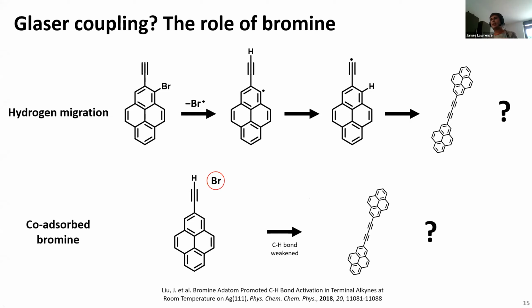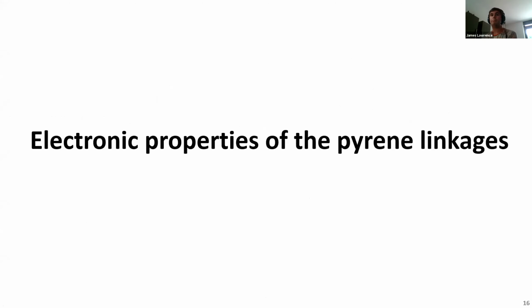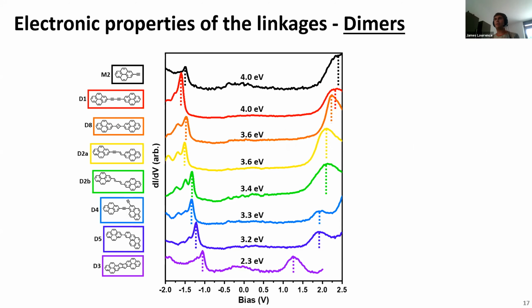come back from this aside and now turn to the electronic properties of the different links between the pyrene moieties. Obviously we've got so many different products on the surface that we can study loads of different types of linkages. So on the next slide, I'm just going to show you a nice wide array of dimers that we've formed. At the top here, we've got a monomer without bromine as a comparison. And in the center, I'm showing all of the dI/dV spectra with the highest occupied and lowest unoccupied resonances indicated with the dashed lines. And we can see how, as we change these linkages, we get quite a large decrease in the HOMO-LUMO gap, which you might expect, especially when you start fusing these rings to the pyrenes in particular.